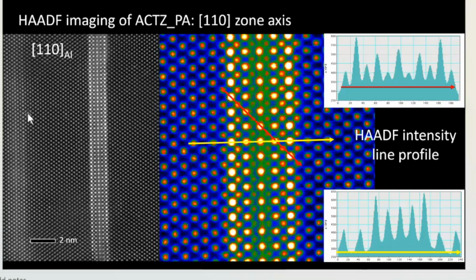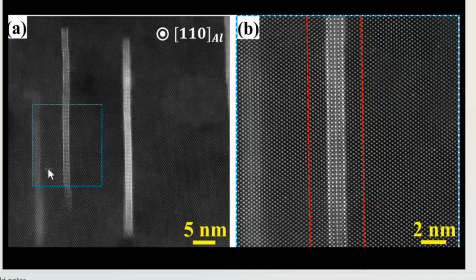But one more interesting thing that we observed, when you look at these plates, for example here, you see they are not a straight line. Plates are not going straight. This is a bit of a zigzag, and one plate sitting on top of another plate in the lengthening direction, slightly displaced. And this is more clearly shown here, that the down arrow shows the displacement, which means this